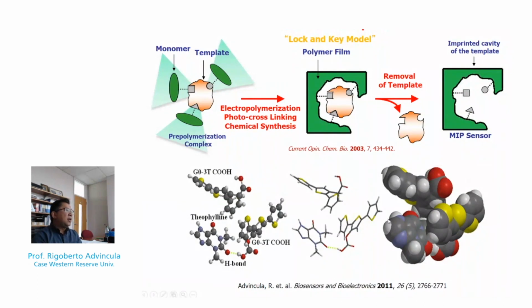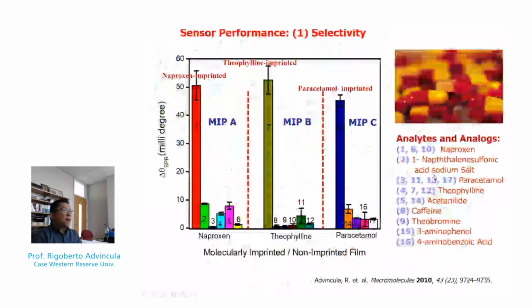So here you can see an ab initio calculation where we complex the analyte, in this case theophylline, with two monomers of the G03T electropolymerizable monomer, and then use this complex to deposit on the film. So I'll just fast forward to the results. The result is you have a very sensitive sensor with naproxen as a template, or theophylline as a template, or paracetamol as a template, with very little response from the other molecules.